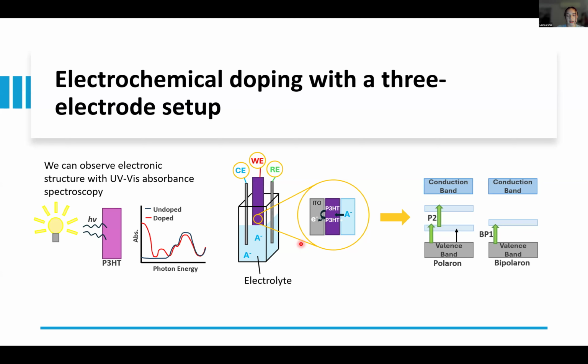But in terms of the new energetic transitions, we're able to observe these with UV-vis absorbance spectroscopy. So when we shine the light, the peaks correspond to the energy associated with these transitions here. And so we expect to see, upon doping, a lower absorbance at the intrinsic band gap here and higher absorbance at these lower energy transitions.